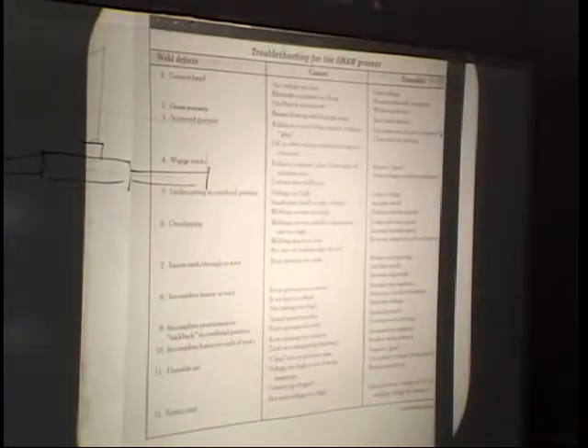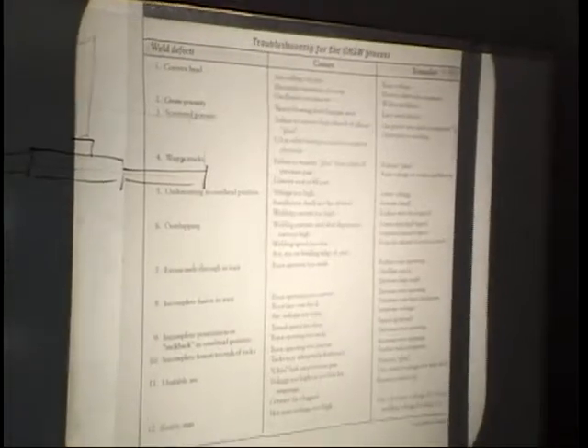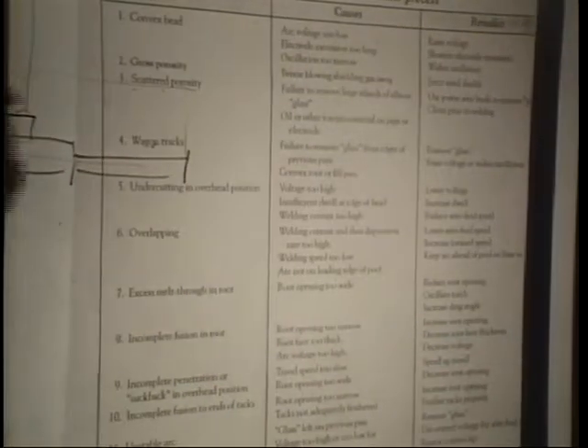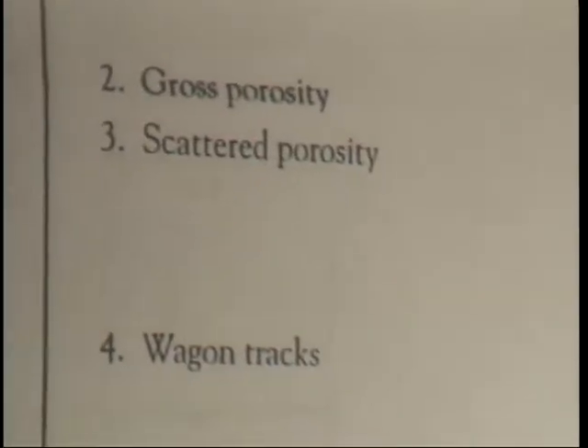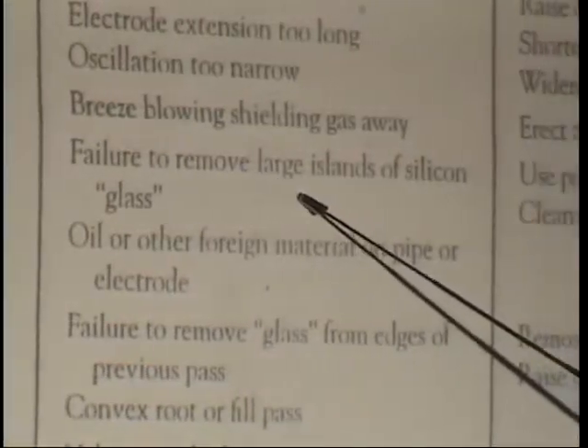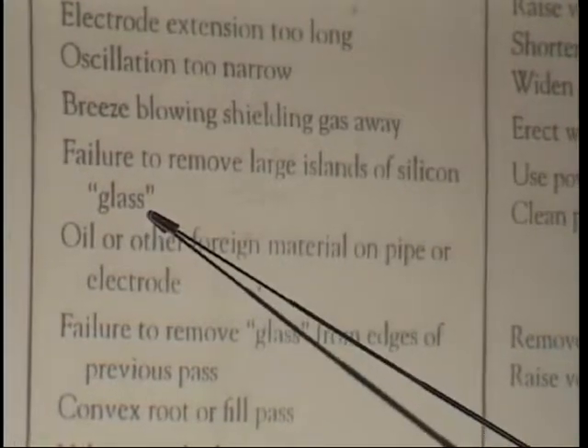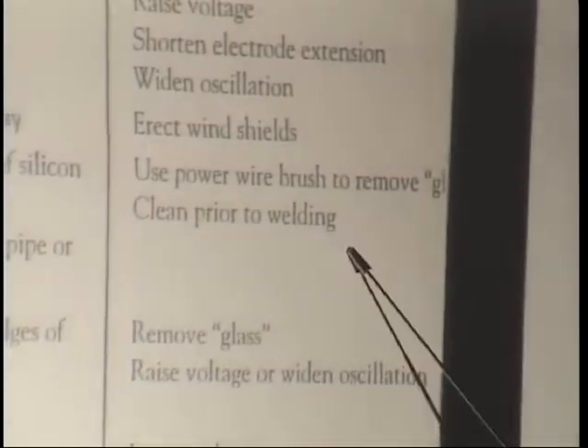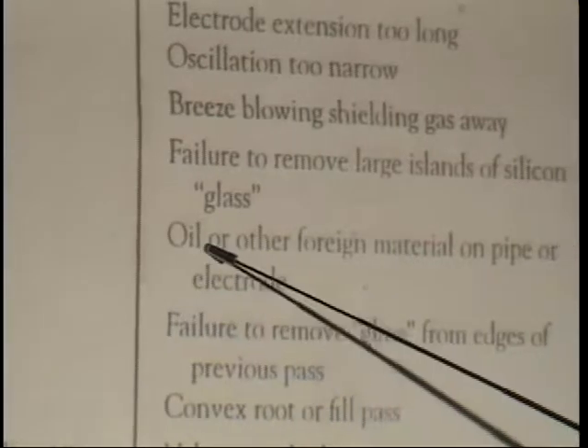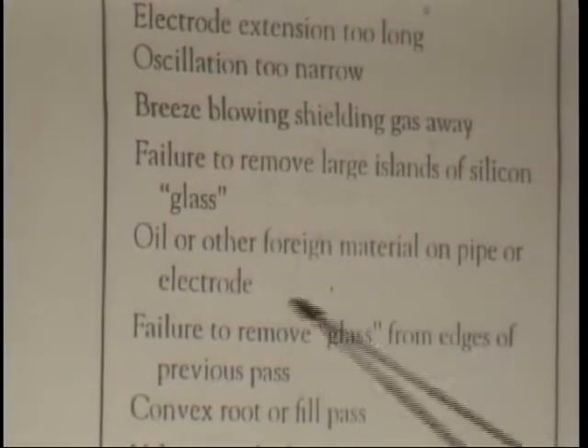The most common things, it says troubleshooting for gas metal arc. What are you going to encounter? Mostly you're going to find number 3 and number 4. Those are the ones that as a craftsperson you're going to encounter in your welding. So what causes it? Scattered porosity. Scattered porosity, it's failure to remove large islands of silicon glass that we've talked about. How would you remedy that? Use a power wire brush to remove the glass and clean prior to welding. And then this is probably the most common one, oil or other foreign material on the pipe or the electrode.